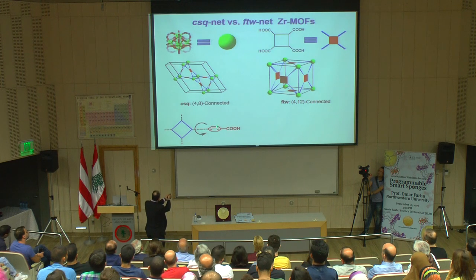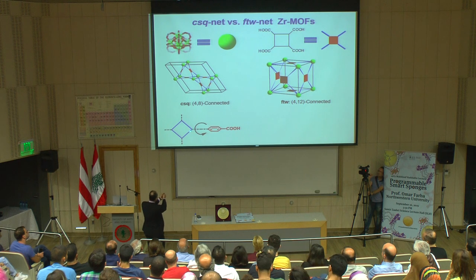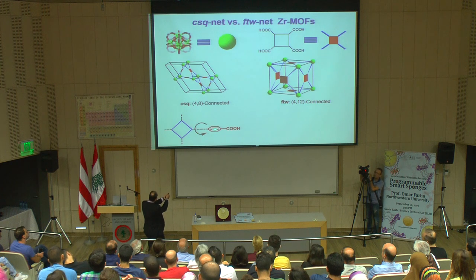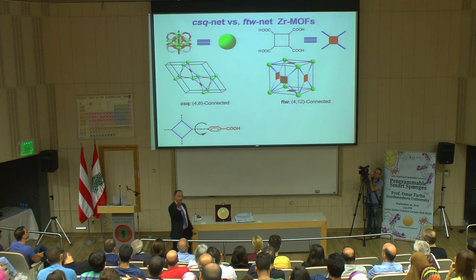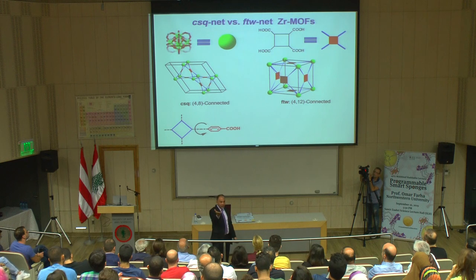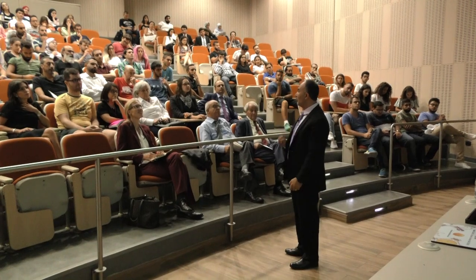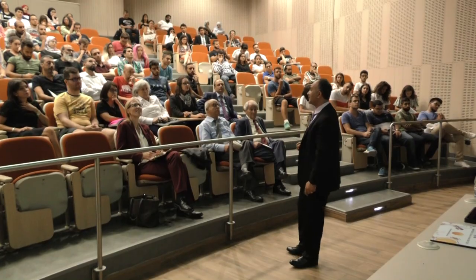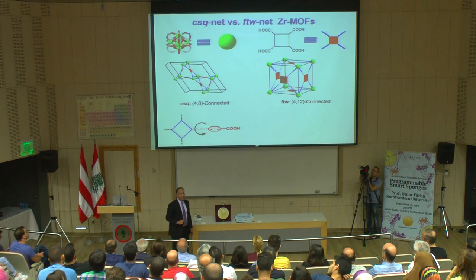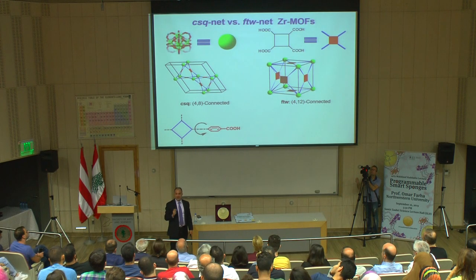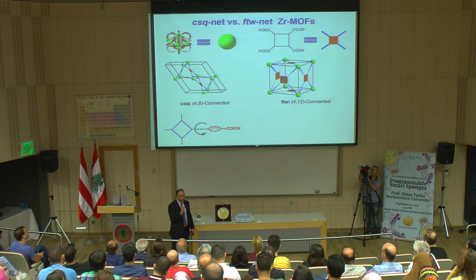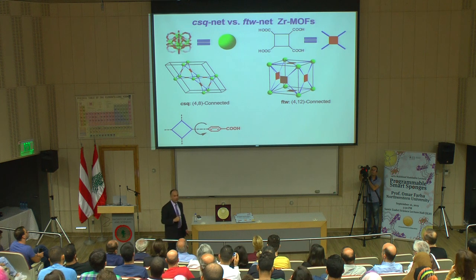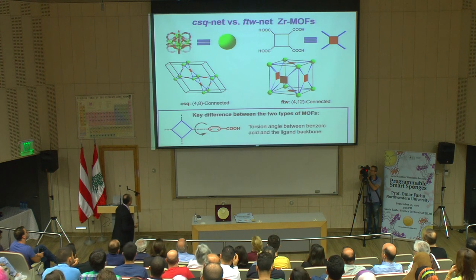Ignore what's in between this benzoic acid at the end of the ligand and the center of the ligand. That does not matter. This benzoic acid matters the most. If the rotation between this benzoic acid and this ligand is 180 degrees or zero, that means it's flat, you will only make the FTW or those boxes. Or if they are 55 degrees to 65 degrees, in principle, they should only make the topology that we want, the two-channel topology. Let's test this hypothesis.